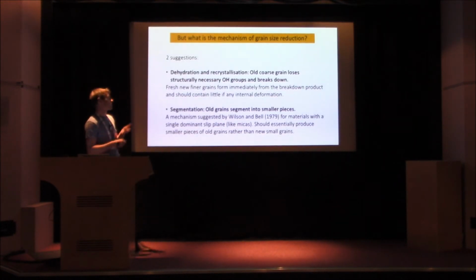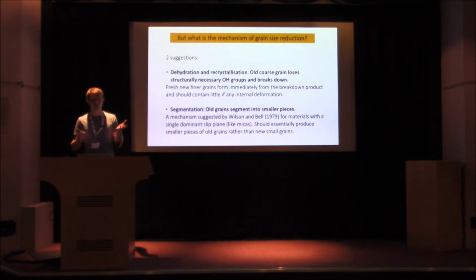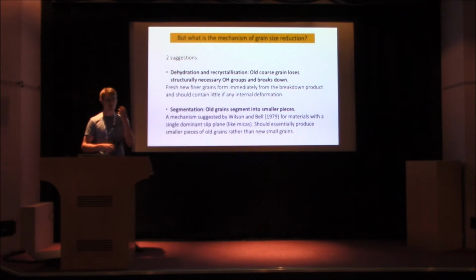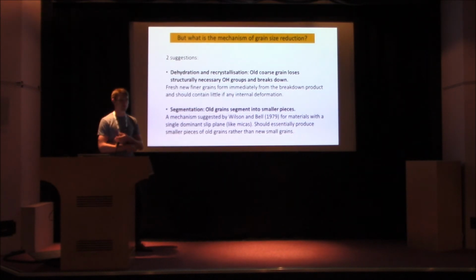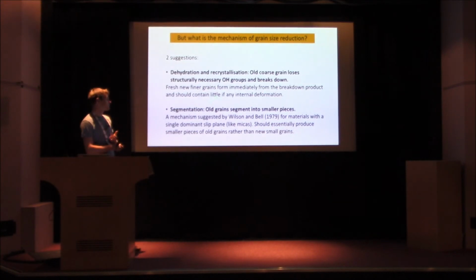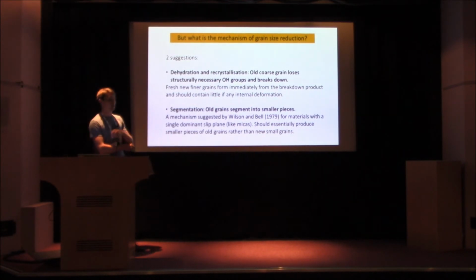So we've got two potential ideas for that. Maybe you've got dehydration and recrystallization. Micas, especially biotite, are hydrous minerals. Within their crystal structure, they contain a certain amount of water. And if you heat them up or if you deform them, you can maybe lose some of that water, and that would cause them to break down and then recrystallize new grains afterwards. So this would be basically loss of the old grain, loss of the old structure, and formation of brand new strain-free grains.